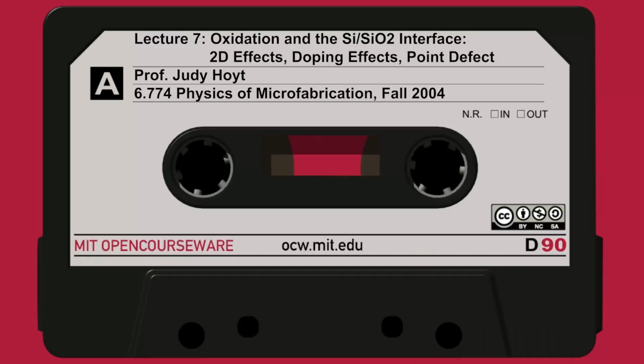In reality, though, if you look at the wafers that come out of the furnace after this 800 degrees C step, these 2 wafers will have different thicknesses. You say, well, how can that be? They're both in the same furnace. They're sitting right next to each other. They had the exact same thickness to start with. Why would it matter? Well, actually, the wafer oxidized at high temperature is going to grow faster compared to the one at 800 degrees because it has lower stress levels. So it has a little bit more open network, so you can diffuse through that oxide more rapidly. And its K sub S, its surface reaction rate, is going to be a little bit faster because it doesn't have the stress in it.